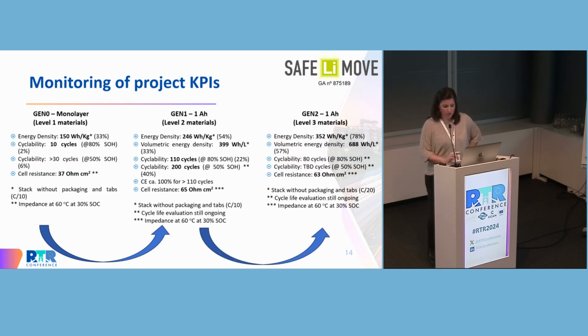And mainly Gen 2, where all the improvements that we apply to the cell and all the learning that we monitor and we gain during the development allow us to reach an energy density of 350 watt-hour per kg and close to 700 watt-hour per liter, and as well reduce the cell resistance. So the cyclability, as I said before, we have 80 cycles, but cells are cycling by the different partners, so results are still ongoing in this regard.